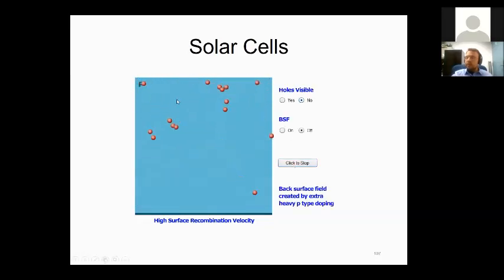This is what we're doing actually. We have these electrons in the p side. Whenever we have electrons in the p side, we would like to make sure that they don't reach the bottom layer here, which is the metal solar cell junction, the place where they meet. There are too many defect sites here, lots of defects like we covered earlier. That creates the opportunity for the electrons to be lost. See, they're disappearing. Once they're created, they have to go to the other side, the N side. They should not come down here.